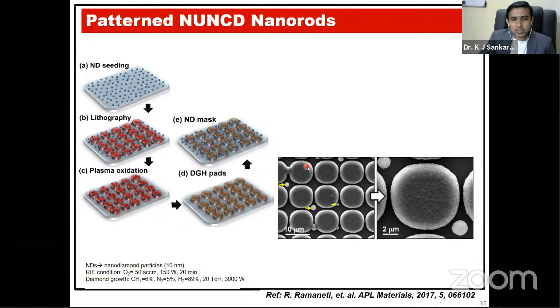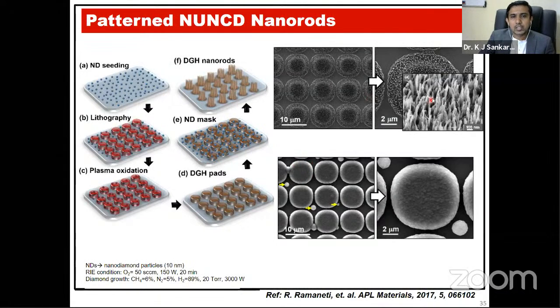The nanodiamond particles will be sprayed on these DGH pads, and then we achieve DGH nanorods, that is, the diamond graphite hybrid nanorods, because NUNCD films have diamond and graphite, as I mentioned in the TEM image. So you can see that vertically aligned nanostructures were selectively grown on these NUNCD pads.